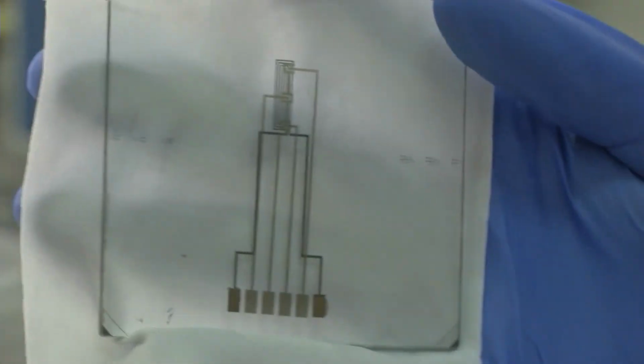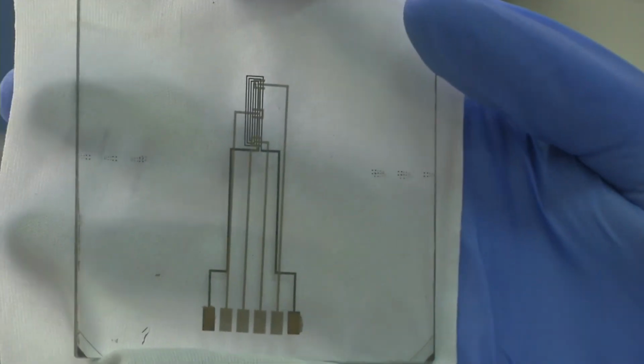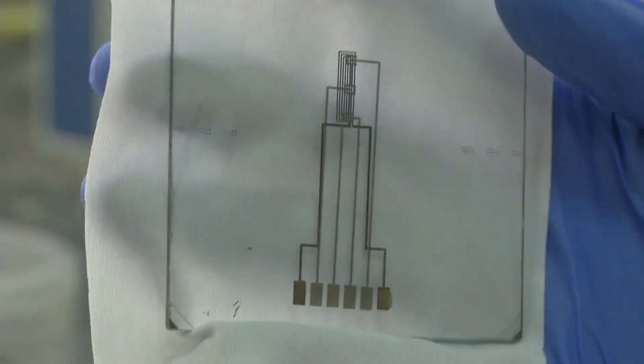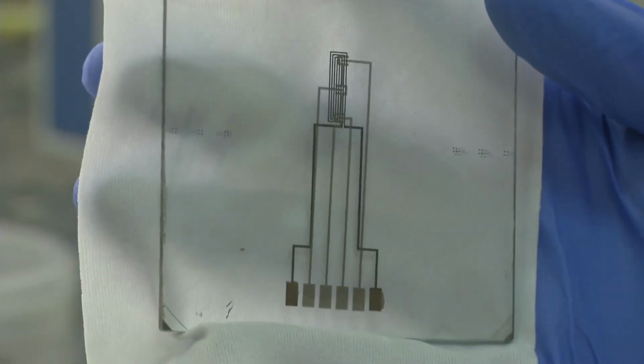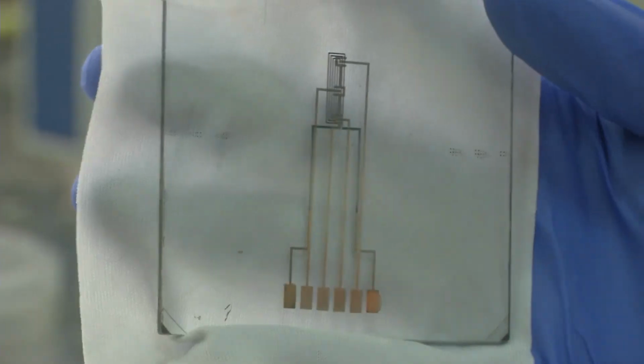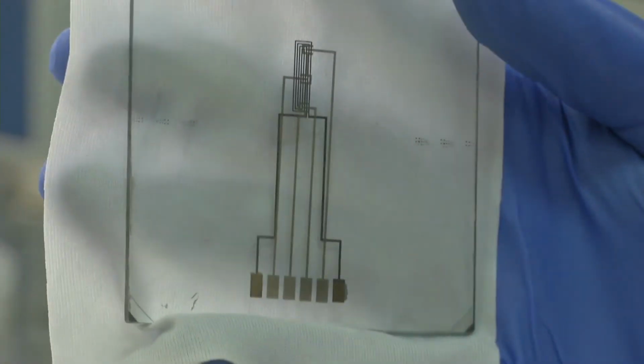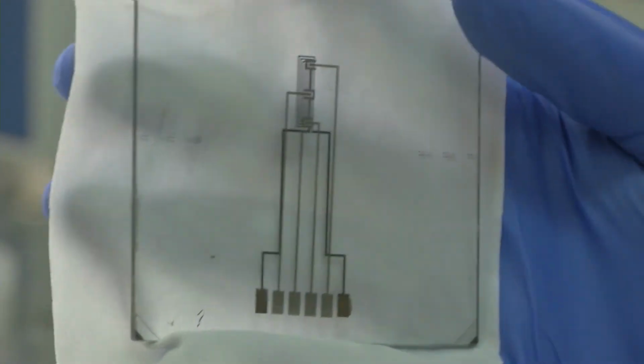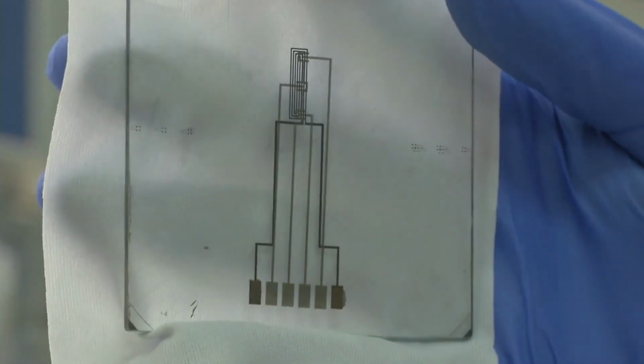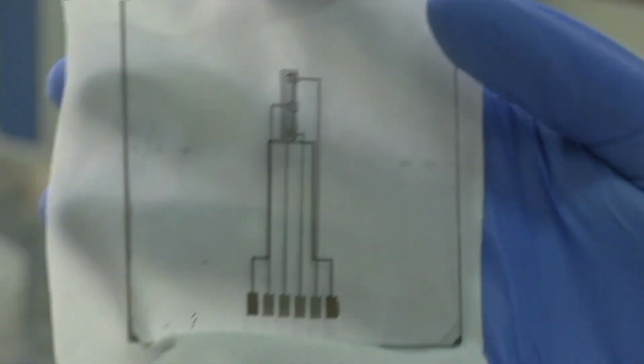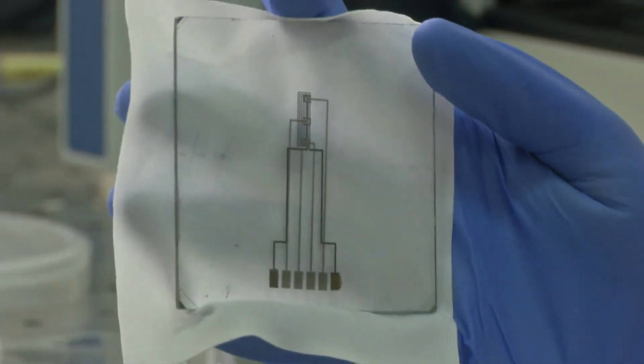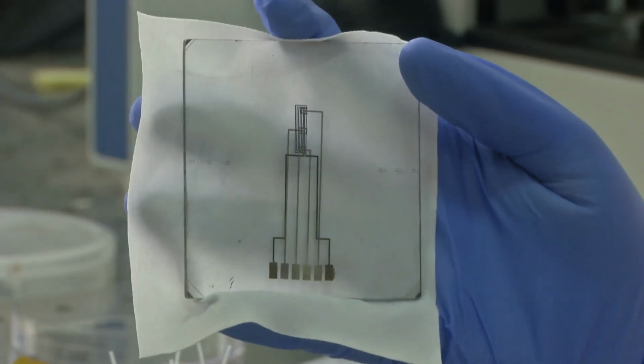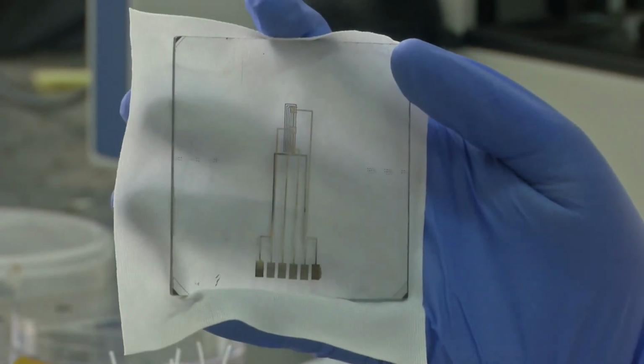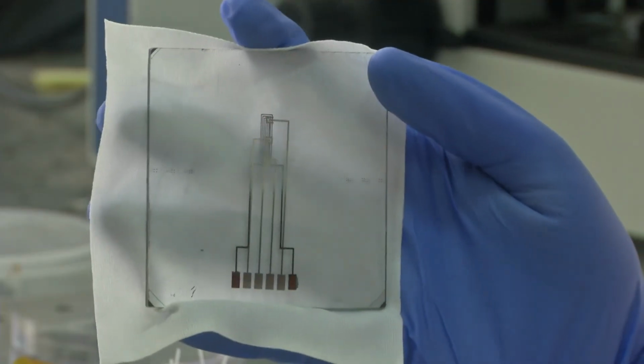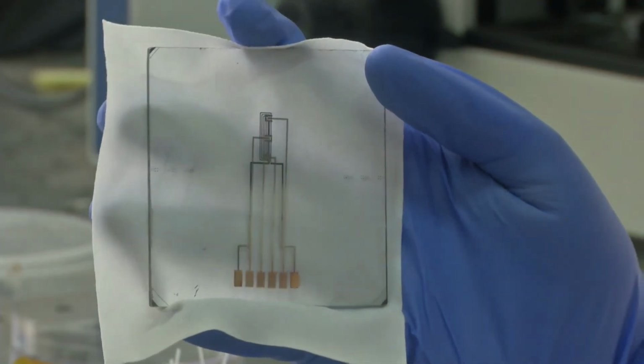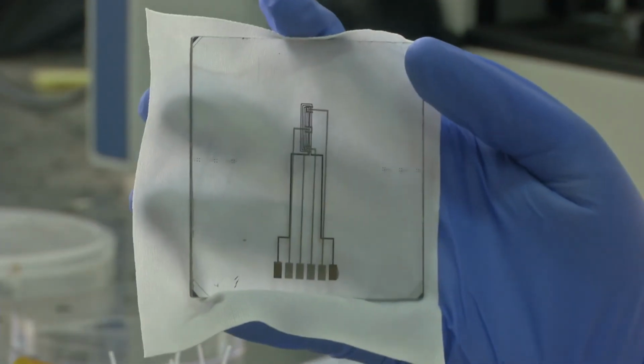The utility of such a structure is this: let's say you are working with live samples. Let's say you are trying to measure the impedance of live mammalian cells or live bacterial cells, and you are continuously measuring it over a period of 1 day or 24 hours. You will be flowing the cells in their nutrient rich media so that they can survive. But for cells to survive, they also need a temperature of 37 degrees Celsius. So how do you maintain that 37 degrees Celsius temperature? For that, we need to have such micro heaters.